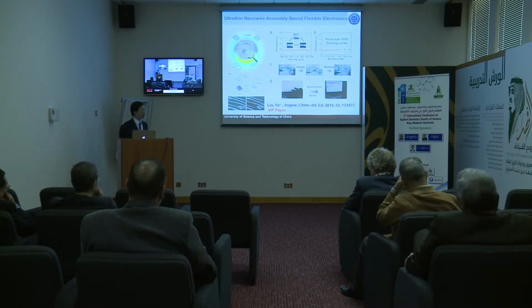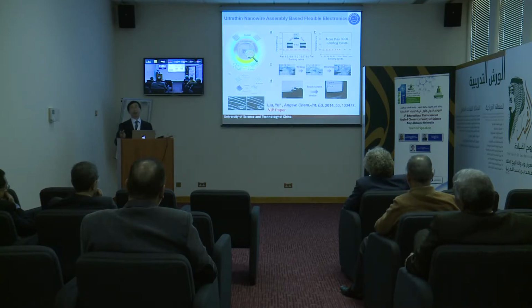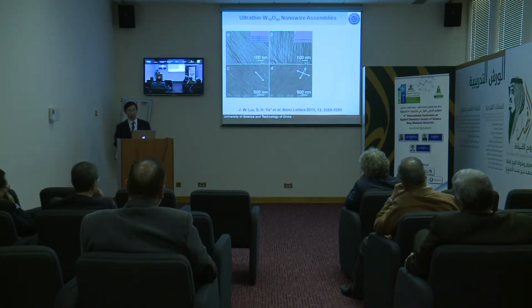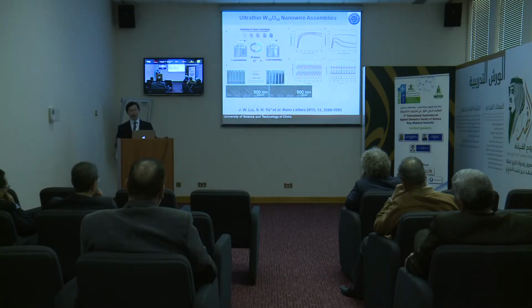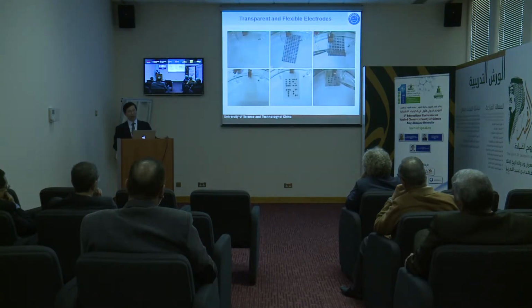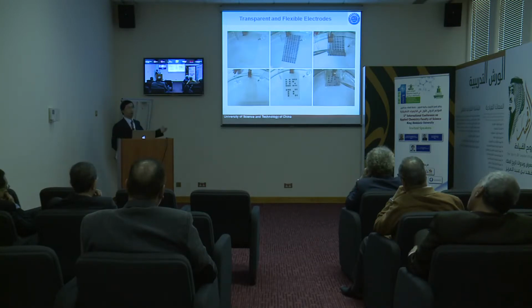the silver nanowire network. So that you can reuse them, if you use them to replace the ITO substrate, then indeed you can use our nanowire system for touch screen applications, for flexible nano devices in the future. And with this nanowire network, we can make transparent, flexible electrodes, or even you can print these nanowire assembled structures on a large size substrate. You can do many things. This is the chrome for the electrochromic